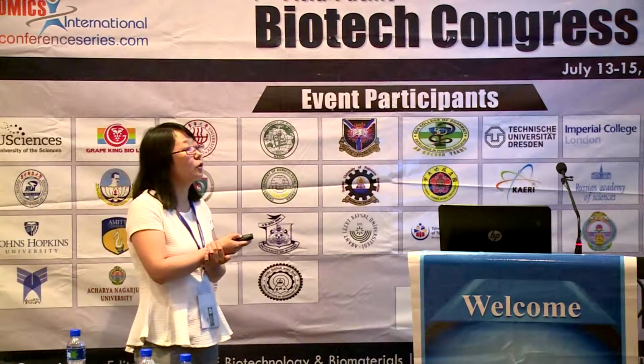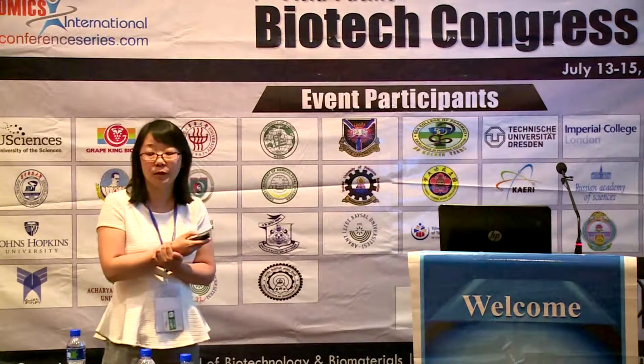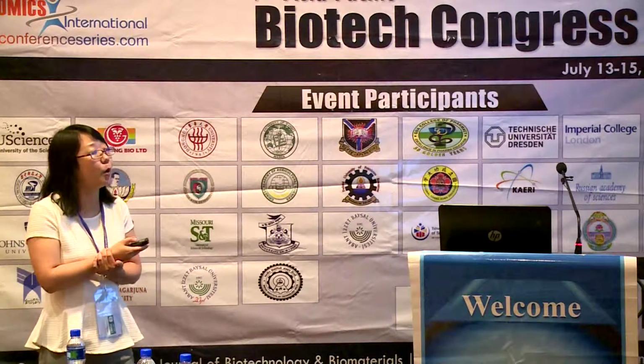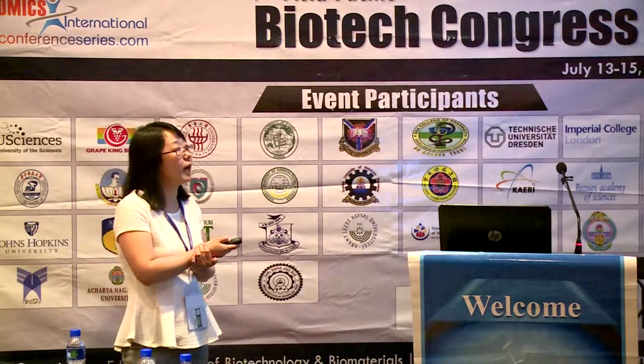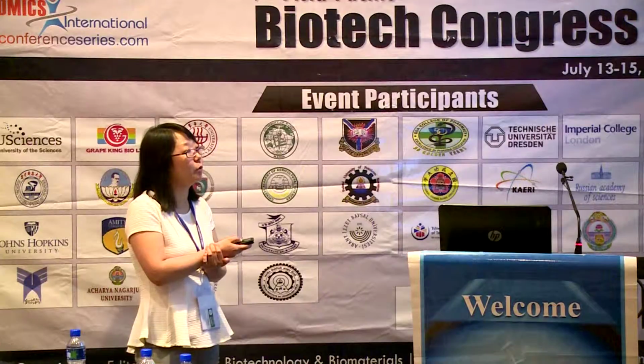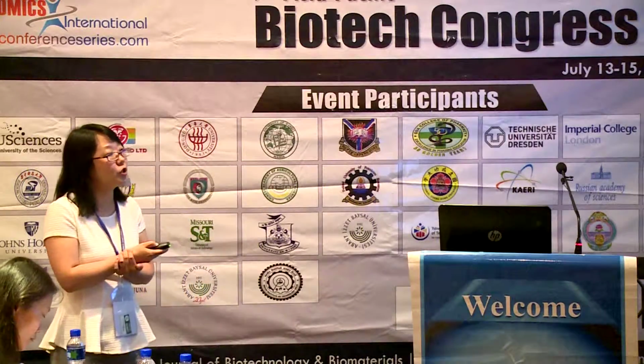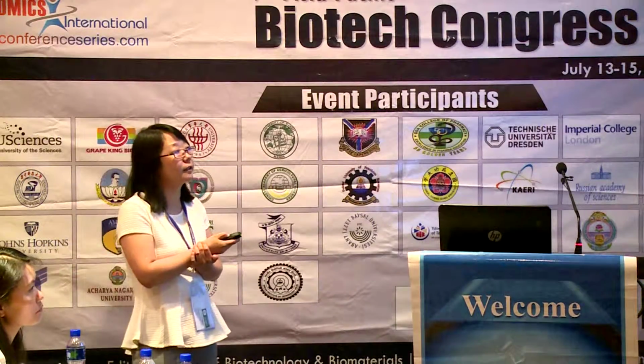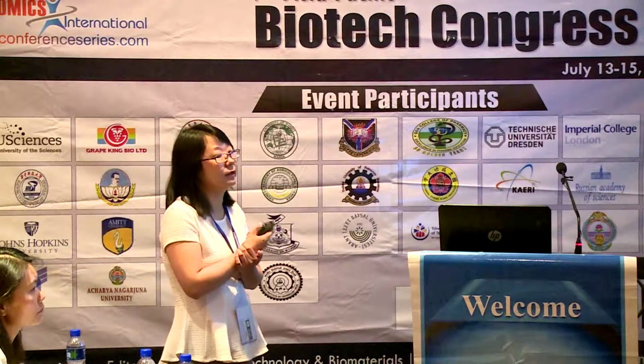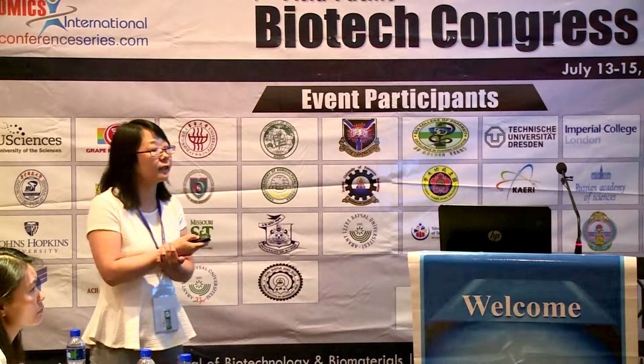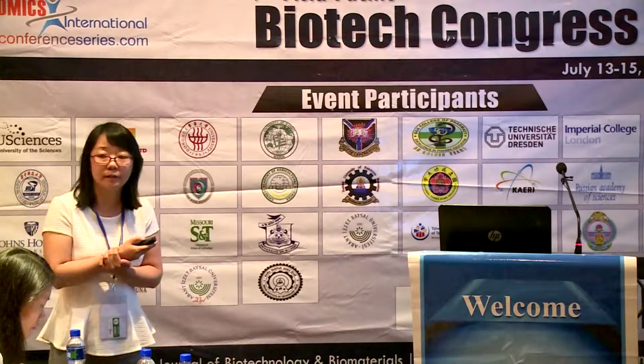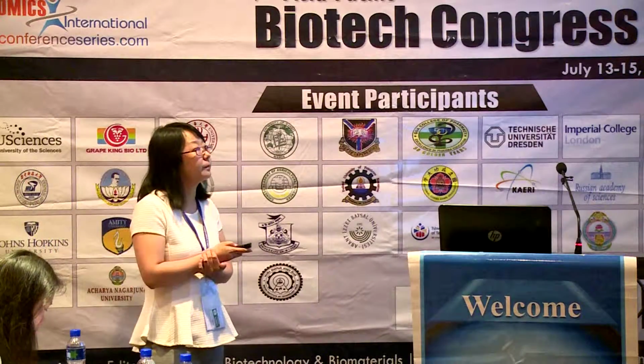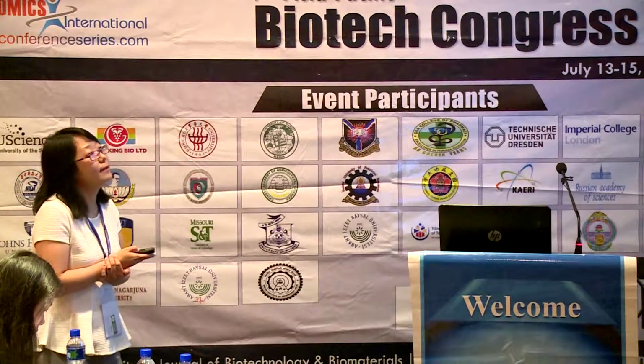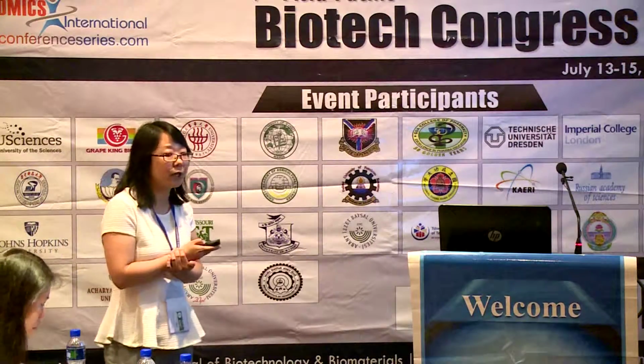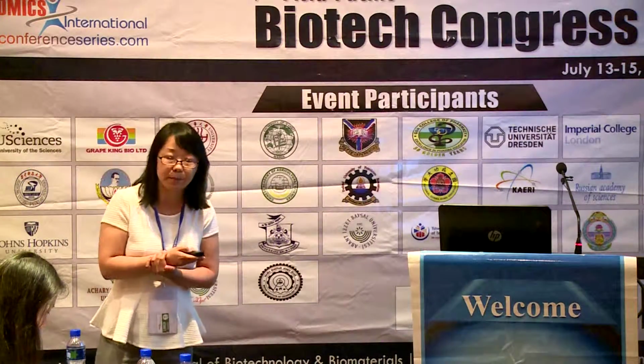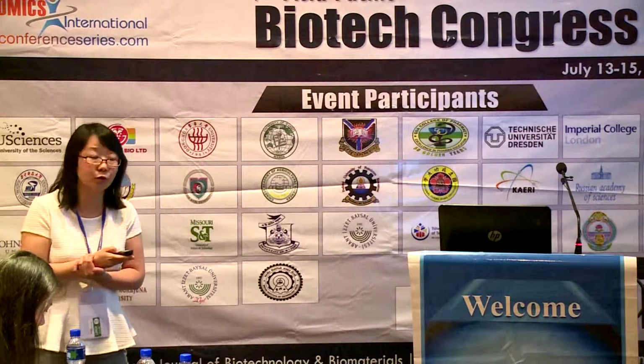The gold nanoparticle is functionalized with a self-assembled DNA monolayer. This monolayer has a sequence complementary to the sticky-end cohesion. So these two different nanoparticles can be exactly controlled in position on the DNA origami template, with exactly controlled distance at the nanometer scale, and self-assembled onto the same DNA origami template with two different chemical reactions.